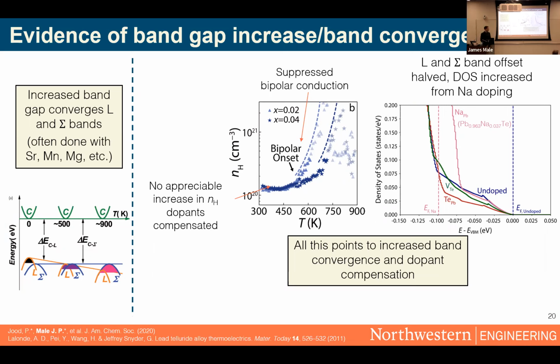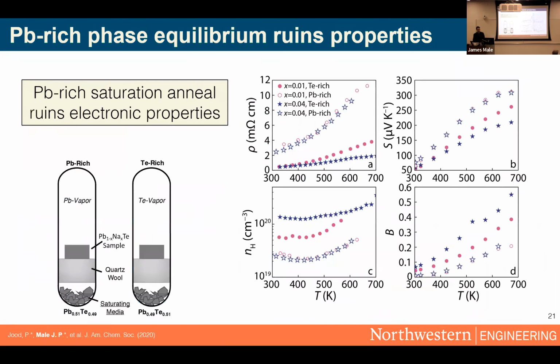We also confirmed this with DFT, which was performed by Shashwat Anand, who found an enhancement in the valence band density of states from sodium doping, but not from any of the other intrinsic defects here. So essentially all the evidence together is indicating that we have this enhanced band convergence.